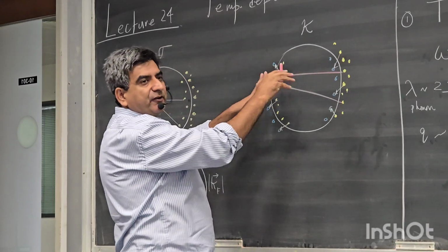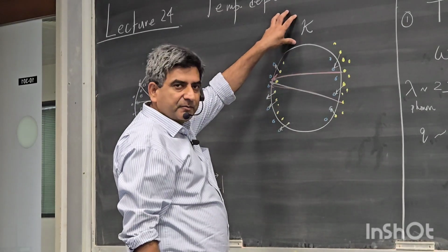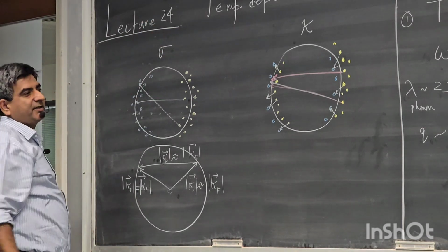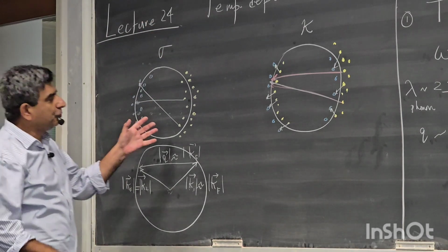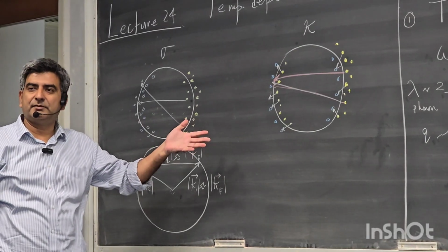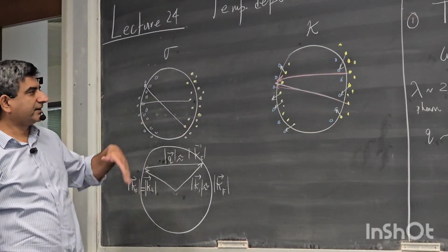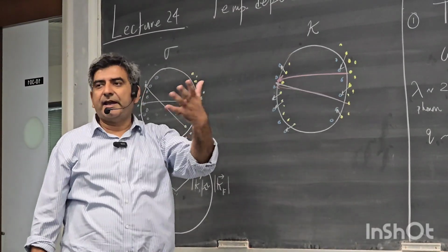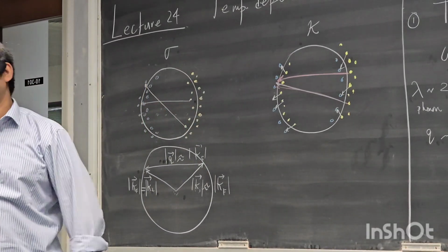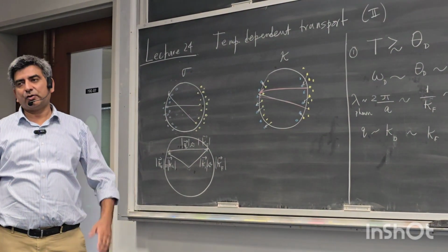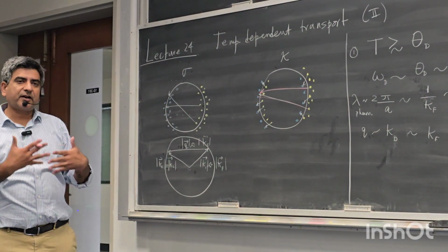So the same kind of process determines thermal conductivity and electrical conductivity at high temperatures. And the two scattering rates turn out to be the same. Therefore, tau sigma and tau kappa turn out to be the same, and L equals the nominal value for the Lorentz number. L is the same as L naught. So this is what happens at large temperatures.